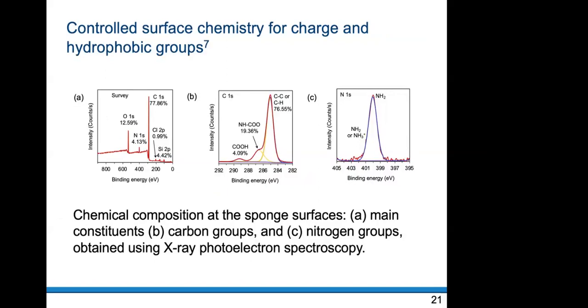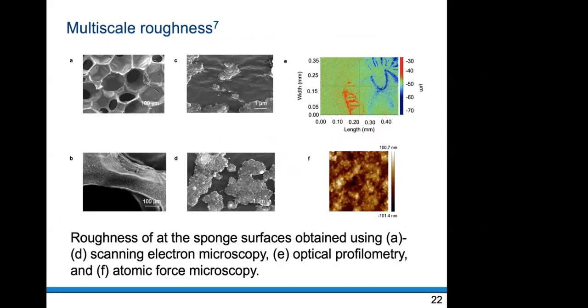After functionalizing the surface, we need to ensure what kind of surface chemistry it has, like how many hydrophobic groups, amine and carboxylic groups, where we can use spectroscopy techniques such as X-ray photoelectron spectroscopy, where we can monitor these different functional groups on the surface and at what concentrations they exist. Also, we can look at the topography of the materials using scanning electron microscopy, where what you are seeing is spherical nanoparticles deposited on the sponge surface. And we can also quantify the roughness of the nano coatings. They provide this multi-scale roughness on the sponge surface, which makes them very helpful in binding the bacteria strongly to the surface. And that can be measured using optical profilometry at the micron level, and atomic force microscopy at a nanometer scale.